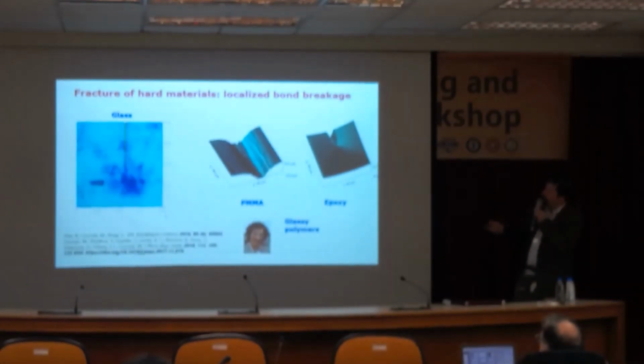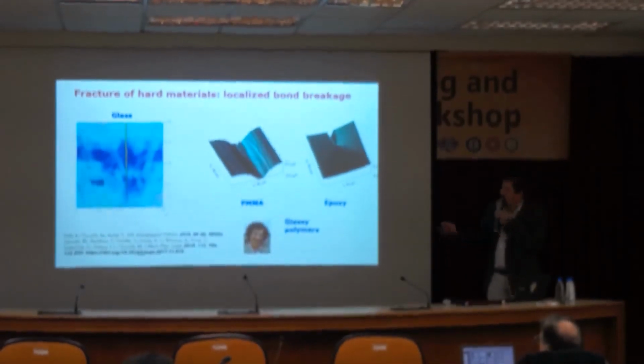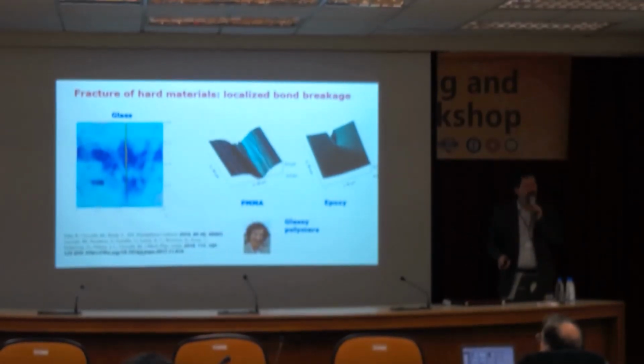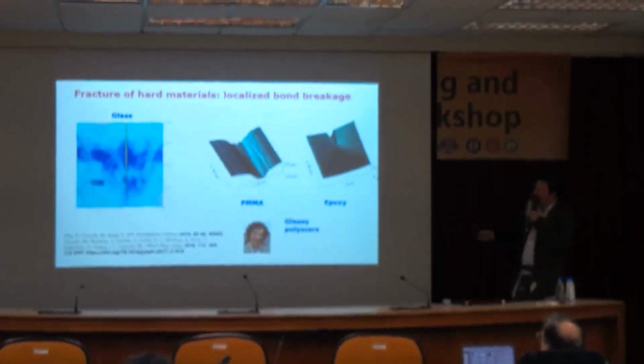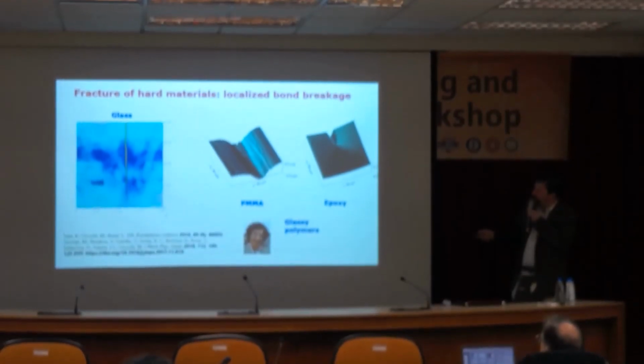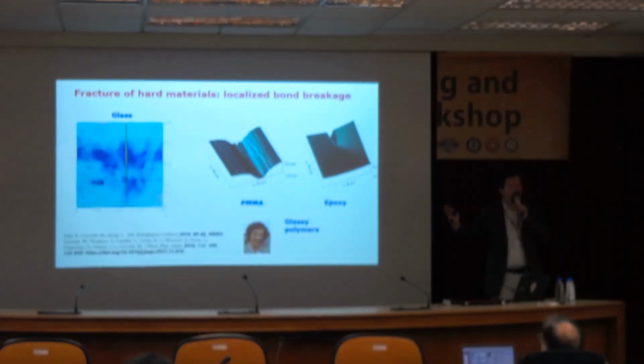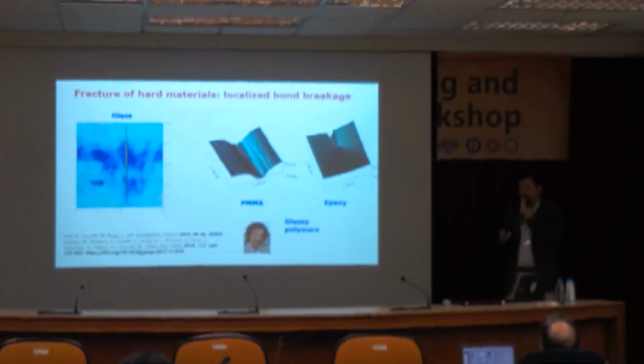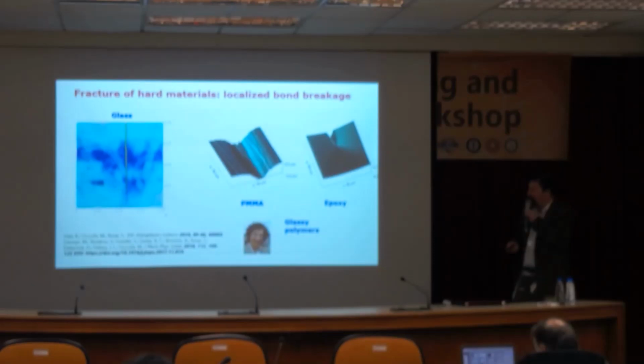This is an AFM picture of slow propagation of a crack in an inorganic glass. This is an AFM, so this is 2 microns inside, and you're looking at something that's maybe 10 nanometers in diameter. So a piece of glass will break by very, very localized bond fracture. This is a hard plastic, PMMA, another hard plastic used in glues. And in this case, this picture of separating the scale between strain energy coming from far away and localized bond breakage works pretty well. We understand this type of problem from the mechanical point of view relatively well.